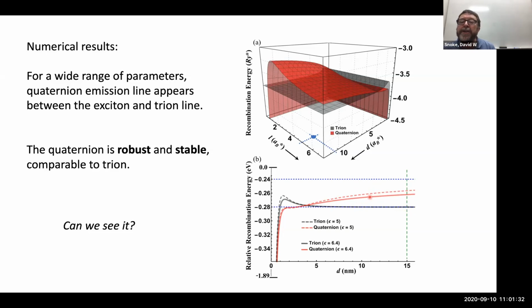Basically the main parameter which is being varied is the screening parameter in the Coulomb interaction. So you have a sort of a screened Coulomb that you have to take into account, and that becomes essentially a fit parameter because we don't know that from first principles. But the same parameter has to be used for the trion, the quaternion, the exciton, and so on and so forth. All right, so let's go to thinking about the experiments.